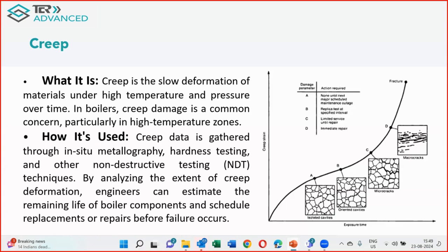Now, here I want to tell you that for compositions which have 2 chrome material and below, when the first creep cavity occurs, we can say that 40 to 50% of life is expended. But if you have the 9 chrome material, very little information is available on this alloy. When the first creep cavity comes, 70% of the life is consumed. So, it depends on the agencies with which you get the life assessment done, which is very, very important in this aspect.